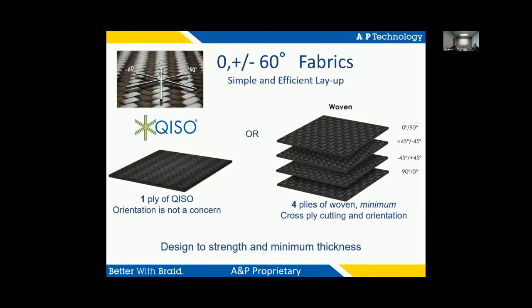Moving to a tri-axial design, our standard product offering would be QISO, which is 0 ± 60, with equal weights of, in this case, we're showing carbon, but we're fiber agnostic, so supplier and material type. So we braid metallics, organics, ceramics, quartz, glass, aramid, etc. But really here with QISO, the fiber area or the fiber yield in the 0 direction is going to be equal to that in the ± 60 by weight, or by yield, excuse me.